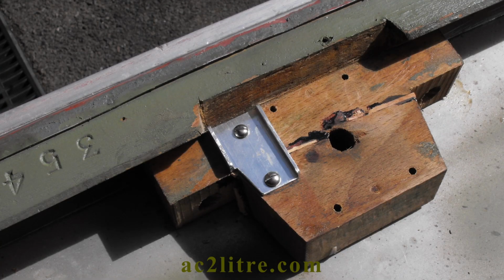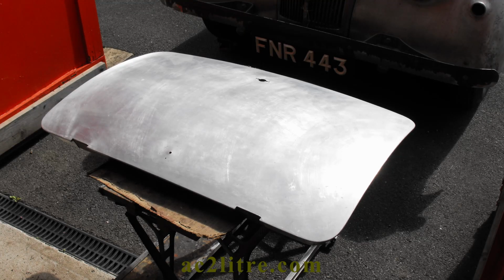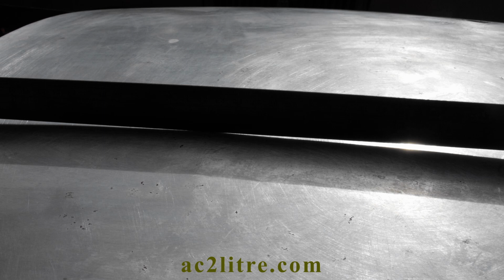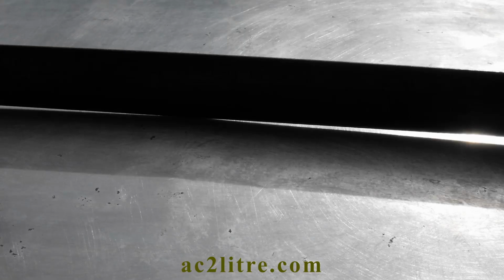After stripping the paint off, I noticed a couple of very slight creases. I believe my dad had caused these. Before I was born, the AC suffered 2 punctures during a family holiday. After that, Dad always carried a second spare tyre, minus its wheel, which he strapped against the boot lid. This pressed the panel down in 2 places, creasing it over the wood frame. As you can see, I got its old curve back.